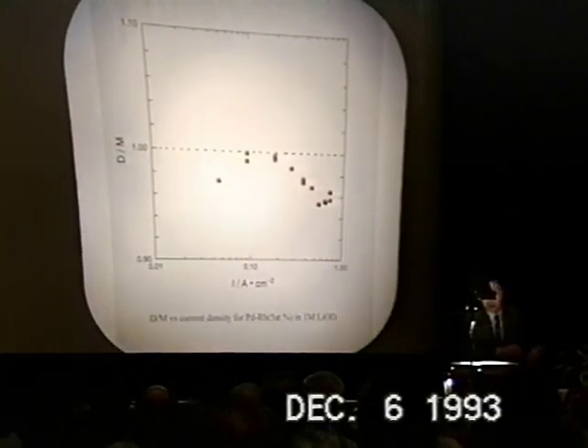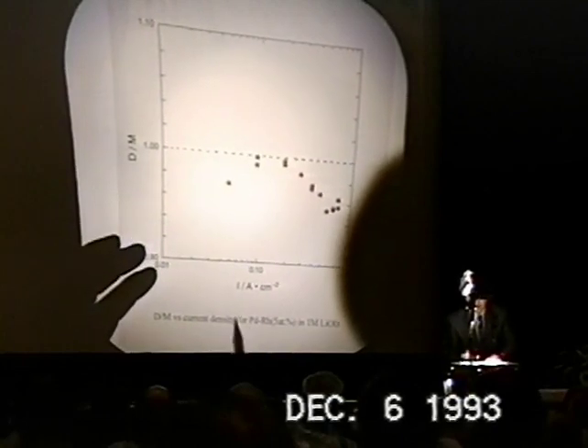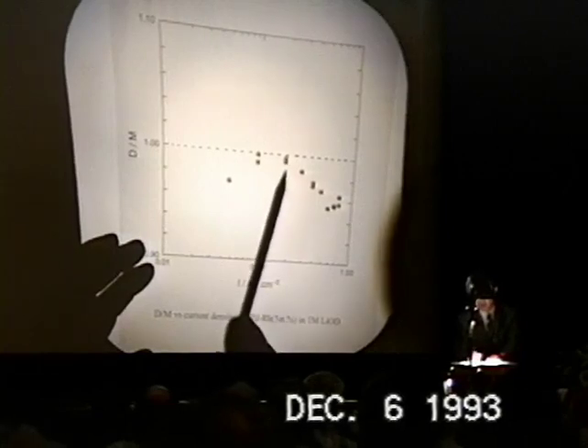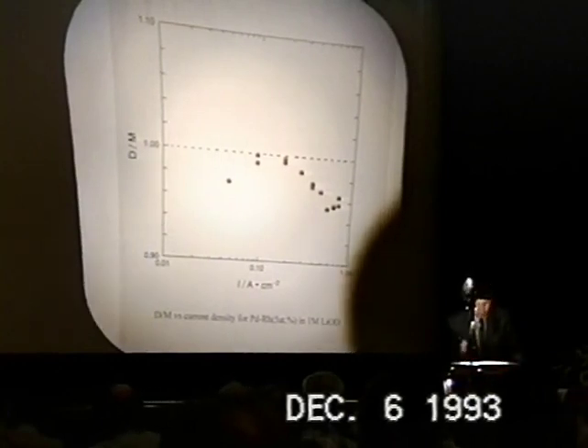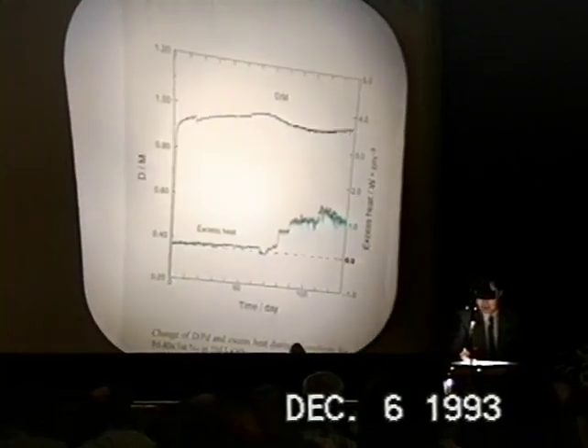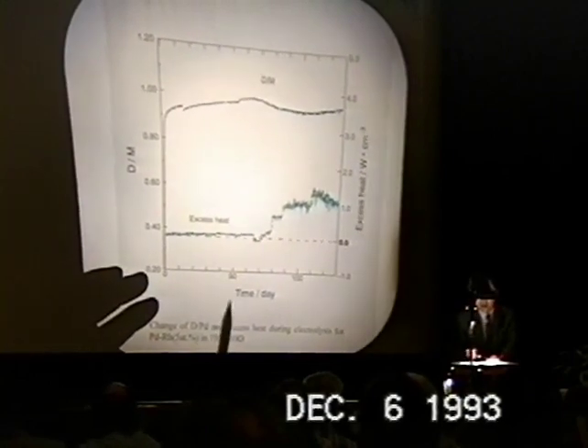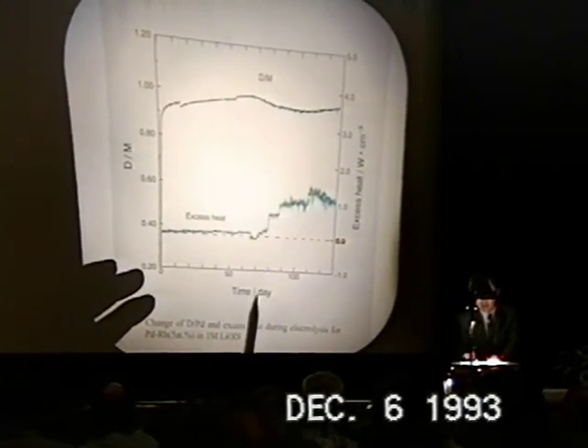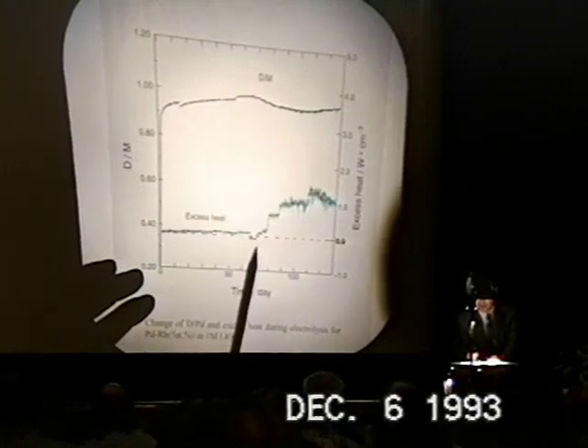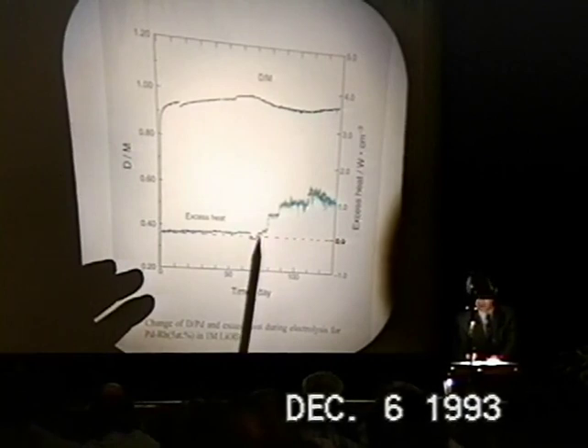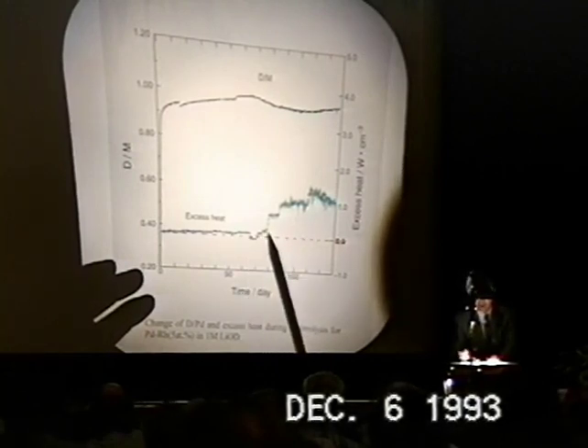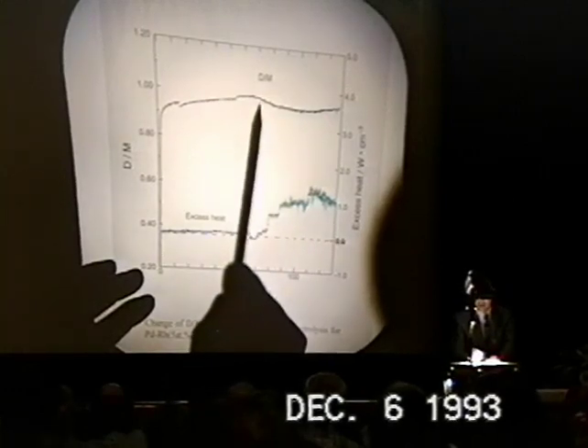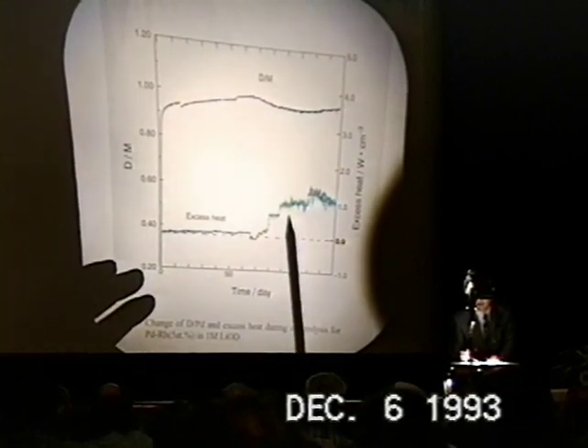So if I summarize this loading data as a function of current density, we have loading ratio nearly 1 at nearly 0.1 amperes per square centimeter. Then it goes down to something like 0.94. The excess heat for this high loading ratio regime, we have this one, the change of excess heat as a function of time. So up to the loading ratio of 1, we see no excess heat, but very embarrassingly, we are starting to see excess heat when the alloy is actually deloading slightly.